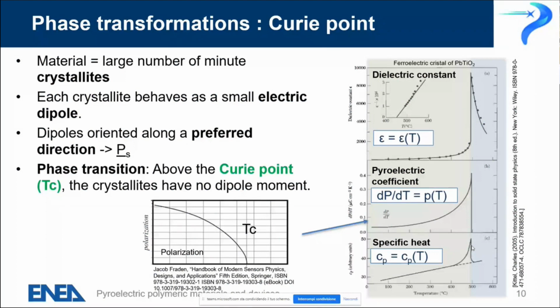Why do we have a variation of polarization? Because the material approaches a phase transformation, a phase transformation that is well described by the Curie point. By approaching the Curie point from lower temperature, the dielectric constant will increase because dipoles can orient more easily under the effect of an electric field. This is due to the change of the polarizability of the material. Then we have an increase of the rate of polarization versus temperature, and then an increase of the pyroelectric coefficient. Simultaneously, we can detect this transformation also if we measure by calorimetry the thermal capacity of our material. Then the effect of approaching the Curie point is a change in the pyroelectric coefficient.